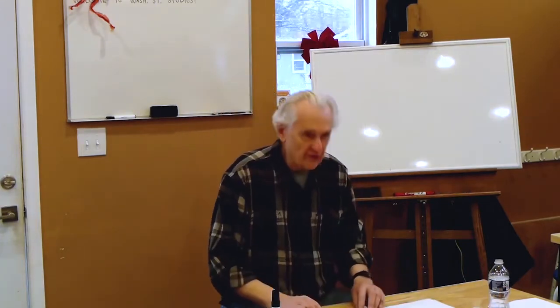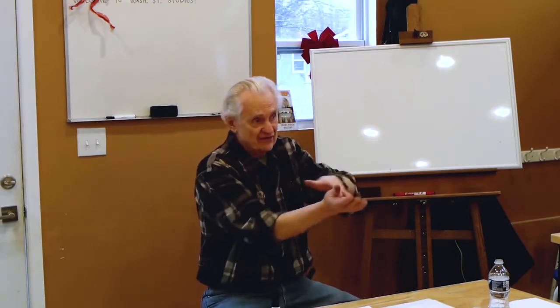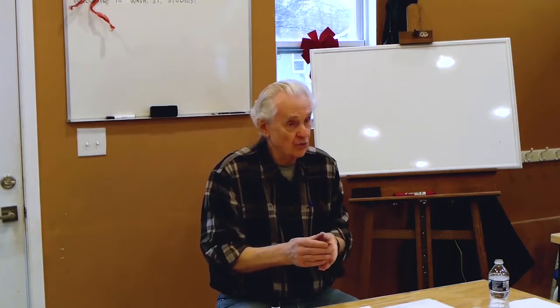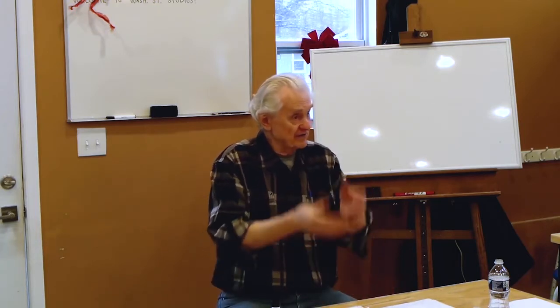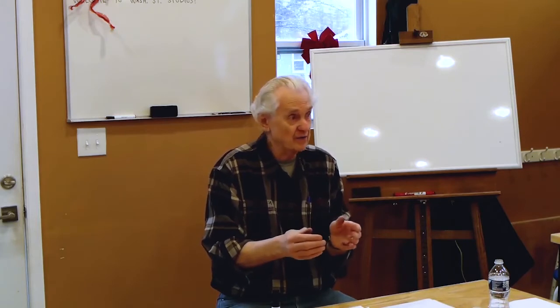Picking up a little bit more in wheel throwing: when we're throwing the clay on the wheel, we're putting compression on the clay between our inside and our outside fingers. We're also creating an awful lot of shear on the clay, because the clay is sliding through our fingers and there's drag. Our fingers are dragging on the clay. That drag is a shear force, tending to smear the clay. So between the pressure and the drag of our fingers, we're orienting the clay particles in the walls. That may not be what we're trying to do consciously, since we're just trying to raise the walls up against the force of gravity, but what's actually happening, and what's even more important, is that we're aligning the clay particles because of that compression and shear.